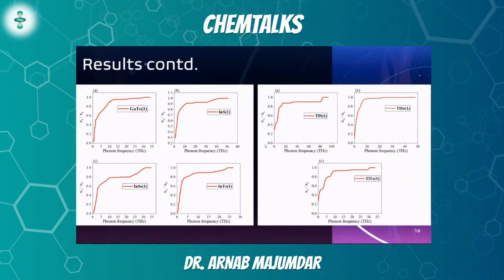Okay, let's check that. Here, it's just a confirmation graph where we have shown that the kappa L, the lattice thermal conductivity, is mostly contributed by the first 5 modes. That is the first 3 acoustic modes and the first 2 optical modes, the low frequency optical modes. And after that, it stagnates, it converges, which means that the higher energy, higher frequency optical modes do not contribute to the lattice thermal conductivity much anymore.